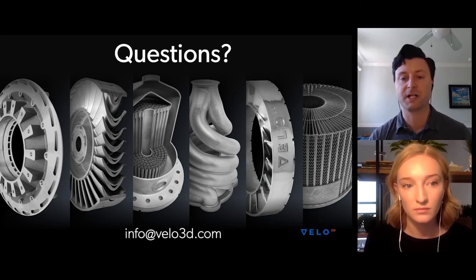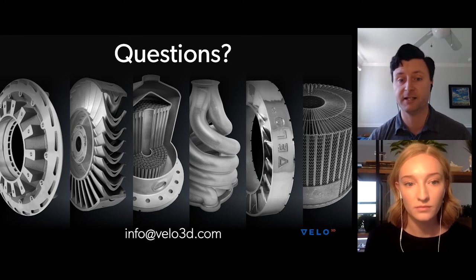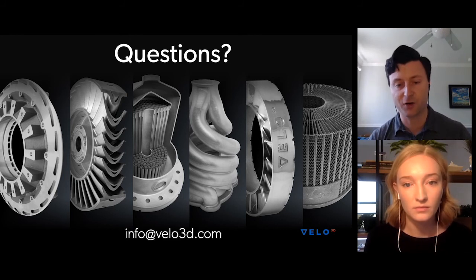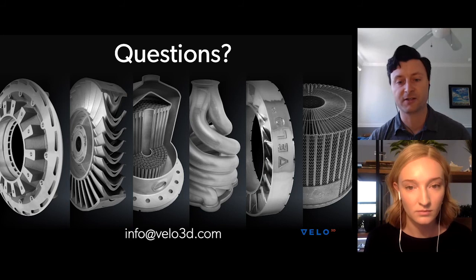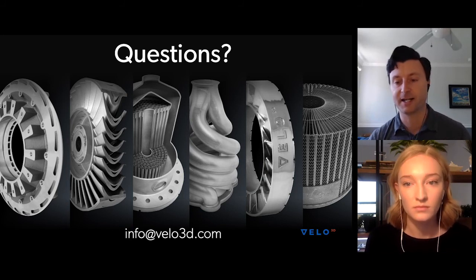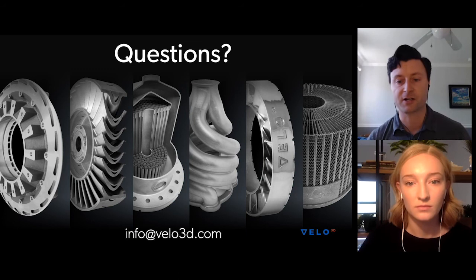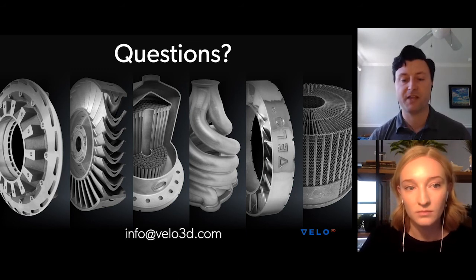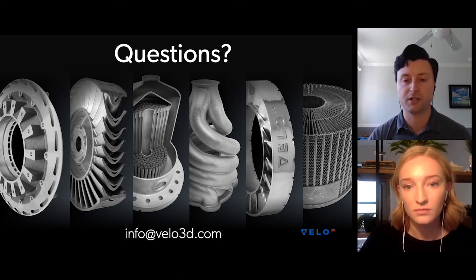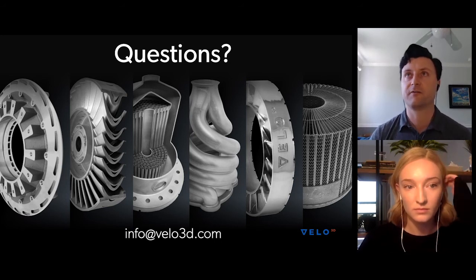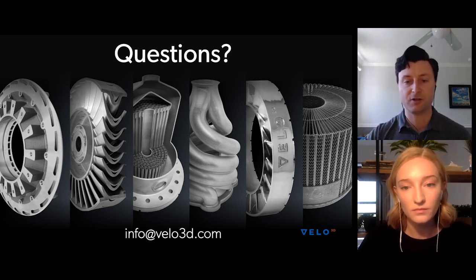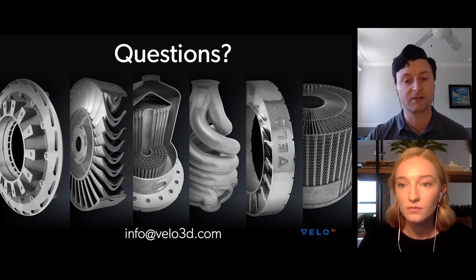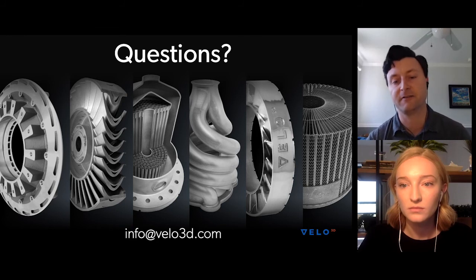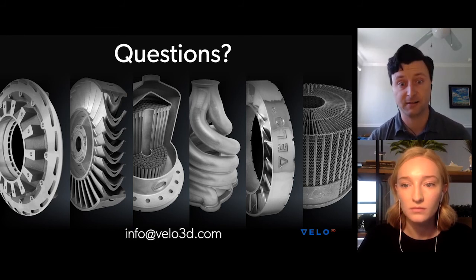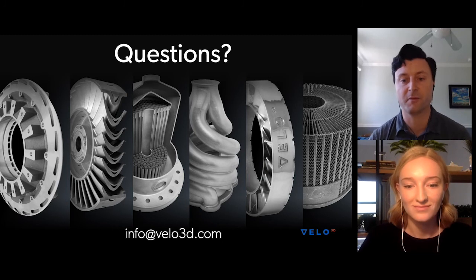Make sure to look at the throughput, because one of the tricks you can play is to slow it down so that you're printing just incredibly, incredibly slowly. And you can start to get away with some of these geometries, but it's just not economical to print if that's how you're actually approaching it. And then on the second question, for a very low angle surface, if you're looking from like the 10 degrees down to a 0 degree overhanging surface, our surface roughness there is probably between like a 10 to 15 micron SA in terms of the actual measurement.